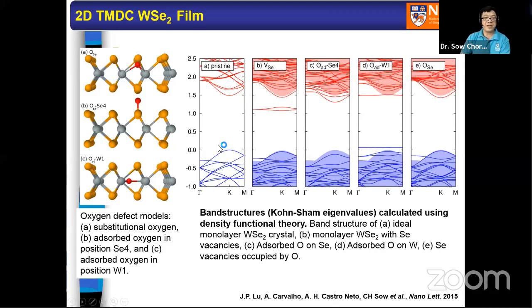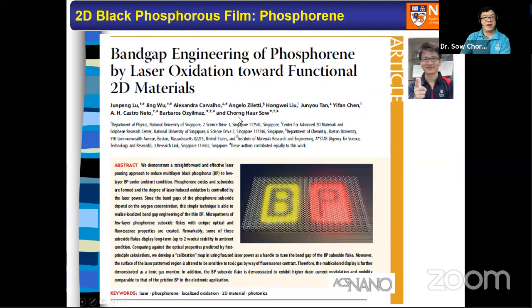And sure enough, when you simulate the band gap for WSe2 with selenium vacancy, you have what we call a charge trap state that is hindering the motion of the electrons. Hence, conductivity will be poor. But with laser beam annealing and healing, patching it up with oxygen, it becomes a state resembling that of a pristine state. And now we have a story of black phosphorus.